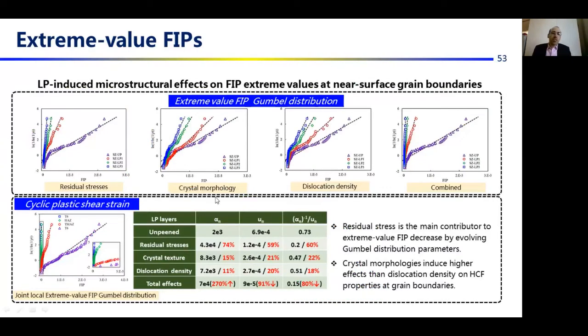For the laser pinning effects on the extreme value FIP, from the statistical Gumbel distribution data, we have the residual stress as the main contributor to extreme value FIP decrease by evolving the Gumbel distribution parameters. It is followed by crystal morphology effect, which has the higher effect than dislocation density because of the decrease in grain boundary misorientation, and dislocation density as a lower effect.